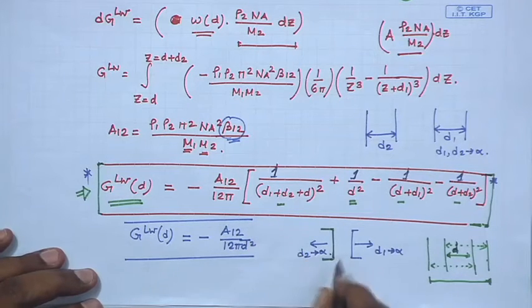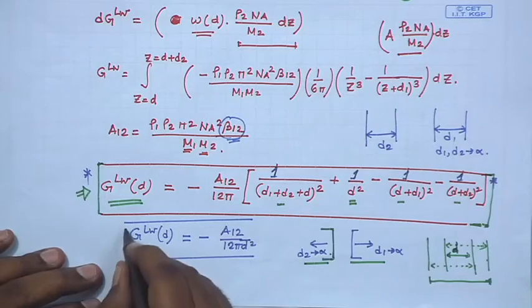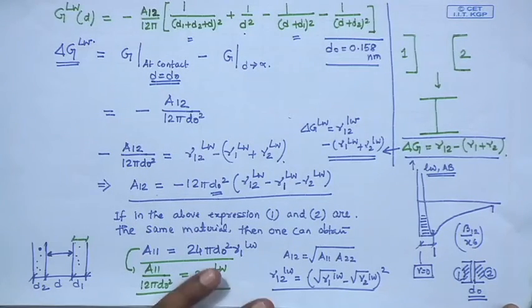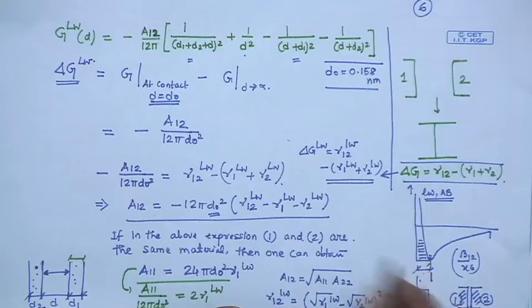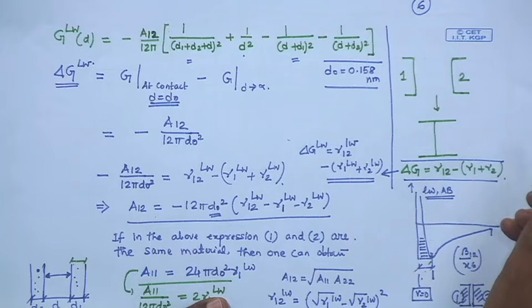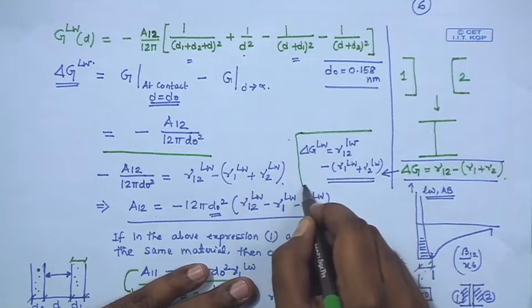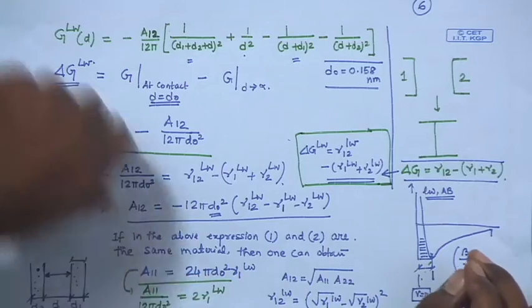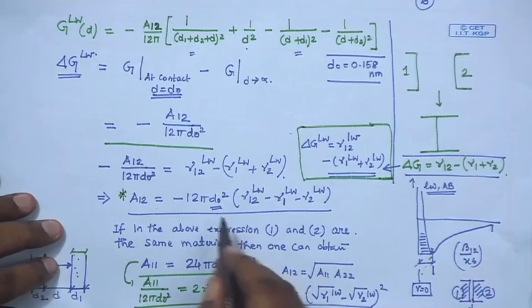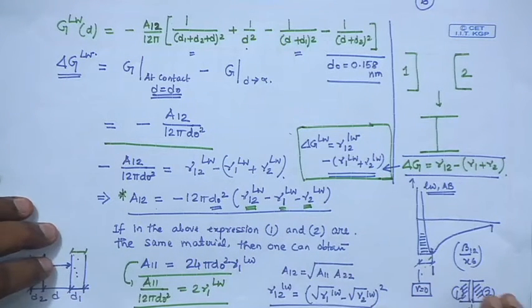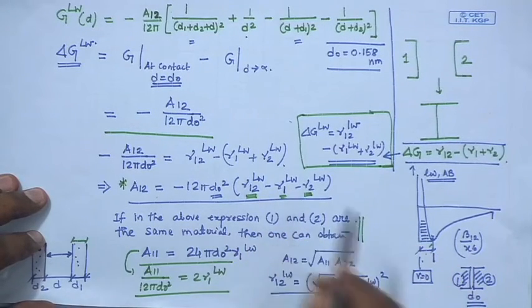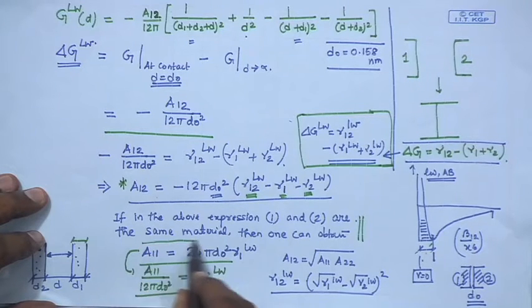We then looked at certain limiting cases. For the interaction between two semi-infinite blocks, GLW is given by a specific expression. We also assumed that at contact d is not zero — there is an equilibrium separation distance d0 — and from that one can calculate ΔGLW comparing infinite separation versus contact. From a simpler understanding one can also get an expression for ΔGLW, equate the two, and obtain a very interesting expression for the Hamaker constant containing the van der Waals components of surface and interfacial energies and d0. By assuming the two materials are the same, one can also obtain an expression for A11.